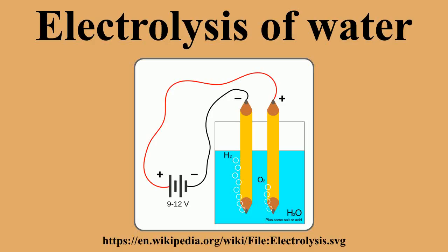If an acid is used as the electrolyte, the cation is H+, and there is no competitor for the H+ created by dissociating water. The most commonly used anion is sulfate, SO4 2-, as it is very difficult to oxidize, with the standard potential for oxidation of this ion to the peroxydisulfate ion being +2.05 volts. Strong acids such as sulfuric acid, and strong bases such as potassium hydroxide and sodium hydroxide are frequently used as electrolytes due to their strong conducting abilities.